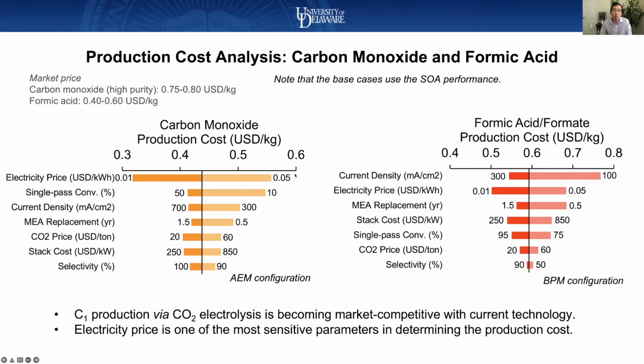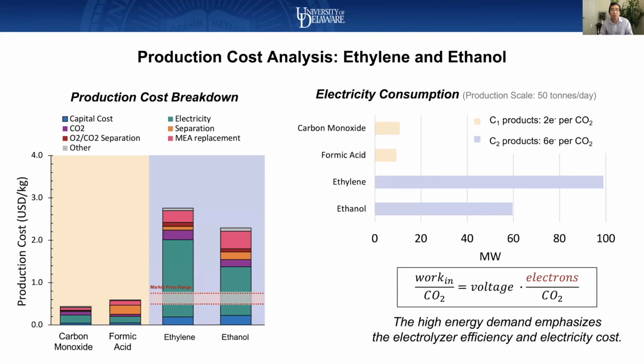If you're interested in multi-carbon products, for example ethylene or ethanol, here is the result. What we found is for multi-carbon products, the production cost is way higher than the current market price, which means that currently, even if you have a state-of-the-art performance system, it's just not cost competitive with existing technology. Why is that? It's because for ethylene and ethanol, you consume more electrons than for C1 products. It's about 6 times more. For example, if you convert 1 CO2 to 1 carbon monoxide, you need 2 electrons, right? If you convert 2 CO2 to 1 ethylene, you actually need 12 electrons.